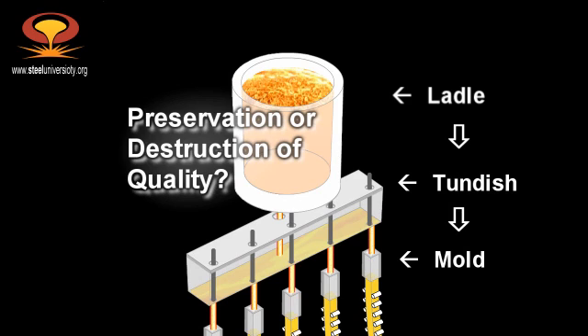Similarly, in the tundish it is possible for vortices to form which can draw tundish slag or tundish flux into the mould. Even in the casting mould, vortexes can form because of the nature of the fluid flow and draw mould flux into the final product. When quality is lost in any one of these reactors, it is difficult to recover that lost quality.